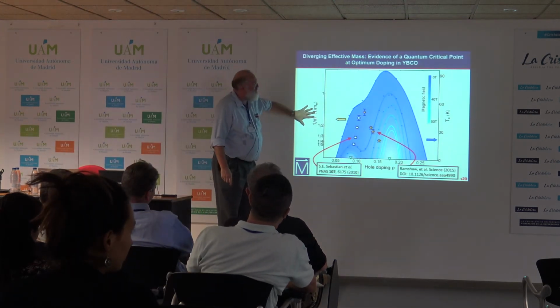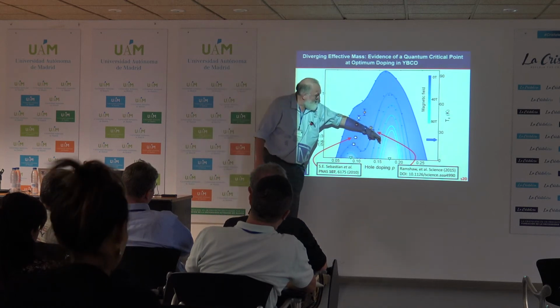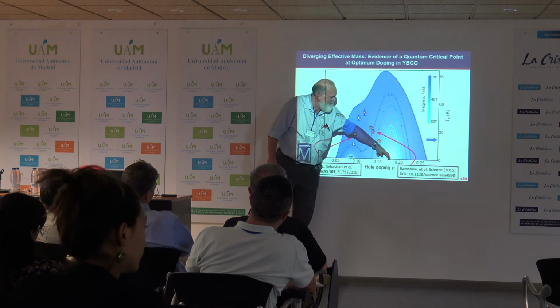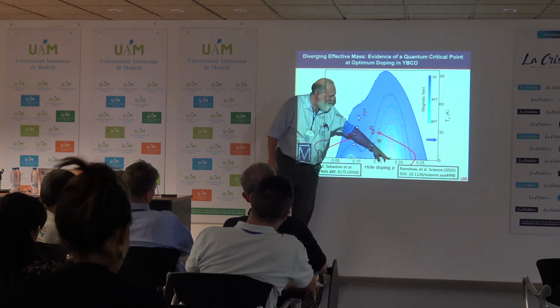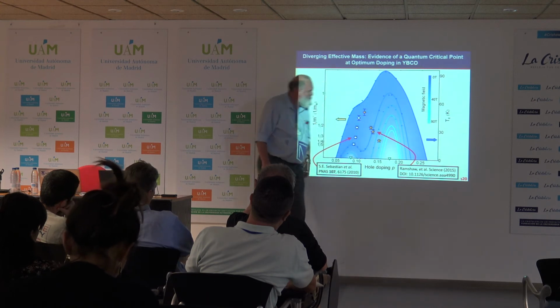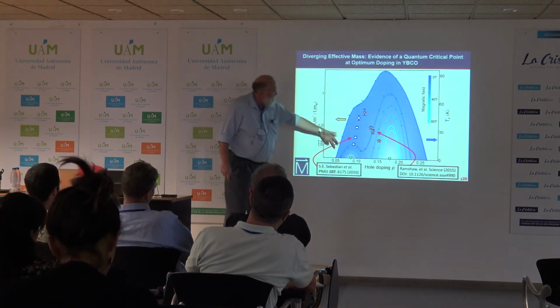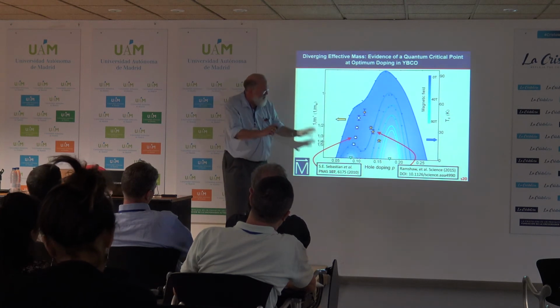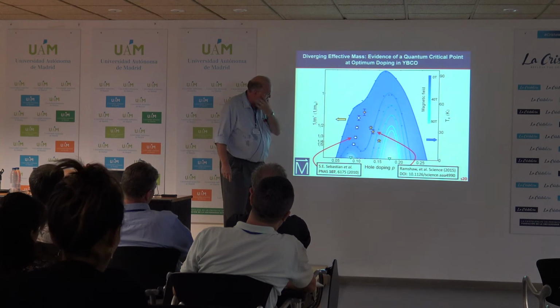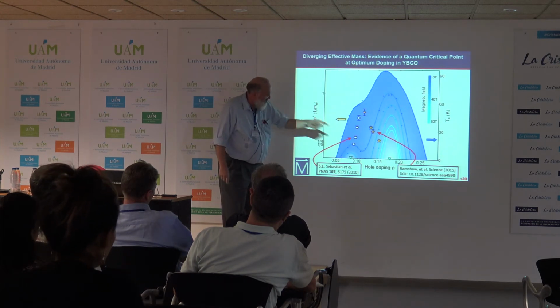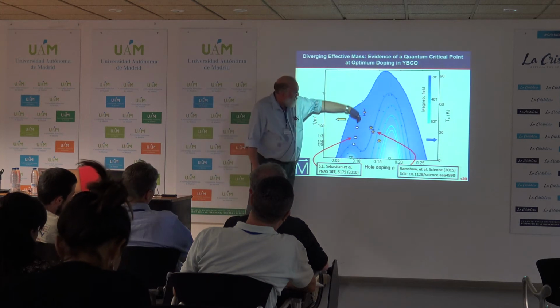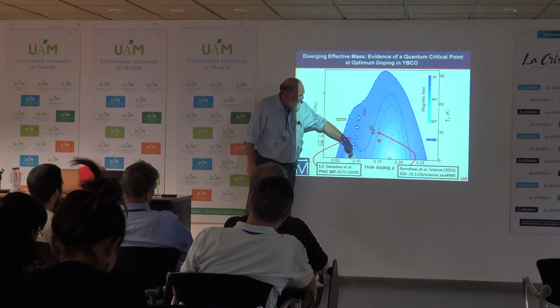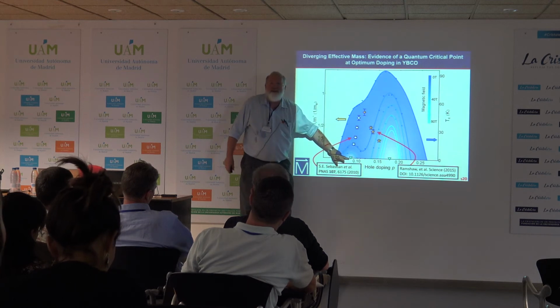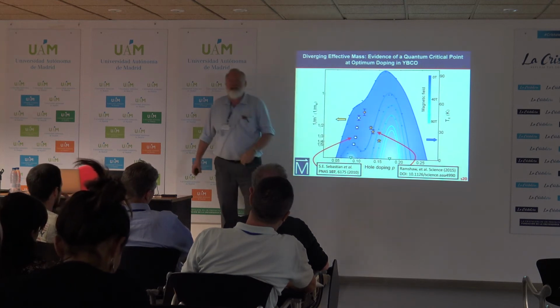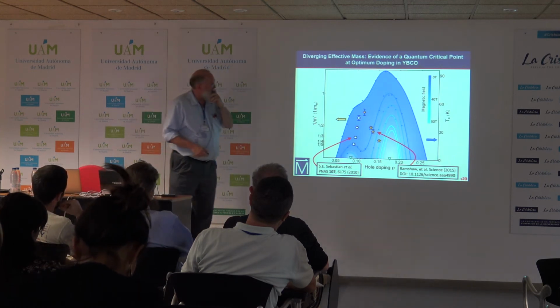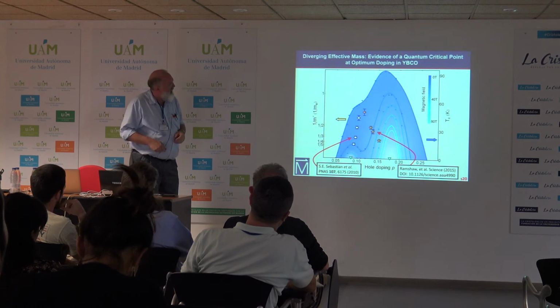And so then he plots 1 over the mass, and you're tempted, as a human being, to make a linear extrapolation, and lo and behold, 1 over the mass would go to 0, the mass would go to infinity, right near optimum doping. Earlier data, from the same group with a few changes in the junior members, headed up by Suchitra Sebastian, who is a co-author on the Brad Ramshaw paper as well, was in this regime, the first samples that showed quantum oscillations, and they seem to show a mass divergence down at 0.08. So at both ends of that phase diagram, I'll show you again, there's evidence of mass divergence. But I'm mostly interested in the optimum doping.